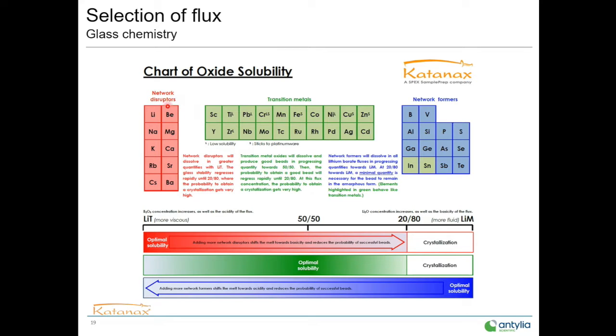If we take a quick example, let's say your sample is mainly made of the red groups here, the alkaline earth elements. The red elements will have the optimal solubility, the best behavior, when the flux is higher in lithium tetraborate proportion. At the opposite, and we see this very often, samples with a high composition of silica or alumina, which are blue elements here, have an optimal solubility and behavior in fusion when the flux is relatively high in lithium metaborate. We see very often people using lithium tetraborate with silica or alumina, which is not a good match. For the transition metals, or samples made of equivalent proportions of red and blue, we will focus on the middle here, so a balanced flux, 50-50 in this case.